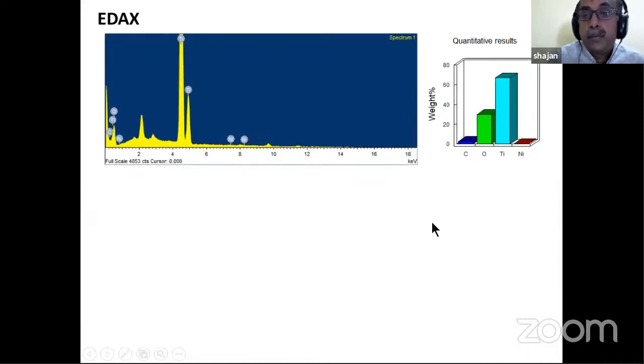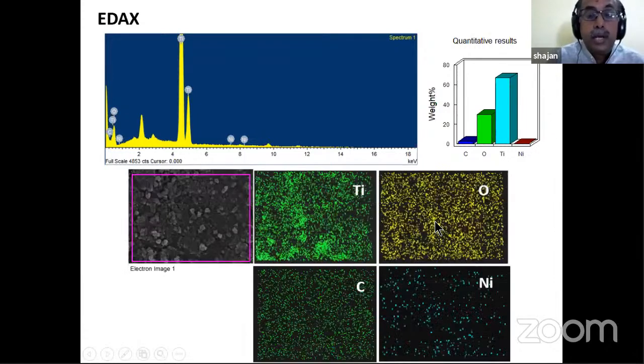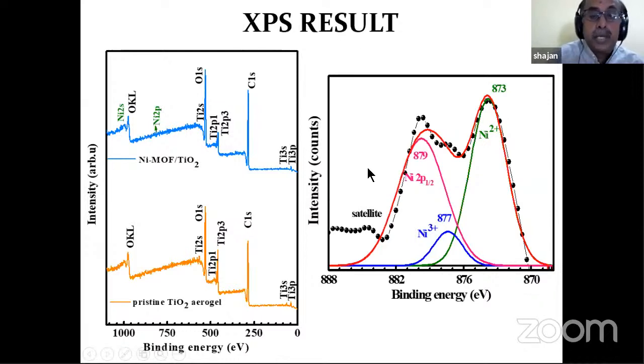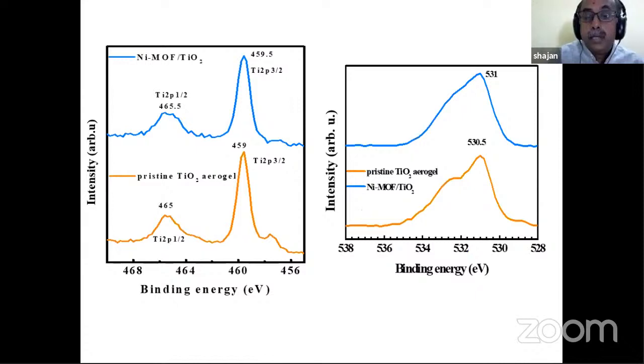And the EDAX was also taken, and the imaging was done with electron imaging. You can see titanium is present, oxygen is present, nickel is present, and carbon, that is from the carboxylic acid, is also present. And if you see the XPS result, it is very clear. You can see the titanium remains in its oxidation state, as well as nickel. This is the pristine titanium aerogel, and this is the MOF added. And you cannot see anything. The titanium aerogel is not disturbed by the addition, to a certain extent.